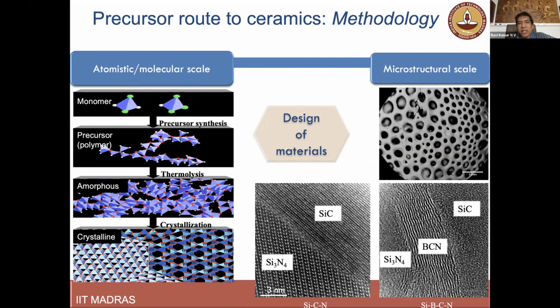Which means that we can design materials at the atomistic scale. And since we are engineers, we look at the possibility of using these materials for certain applications. So it's important for us to also design these materials at the microstructural scale. I show you one micrograph on the top, which is a highly porous ceramic, which can be used either for structural applications or functional applications, because they have very high surface area. The two transmission electron micrographs, which I show you here, are very beautiful.